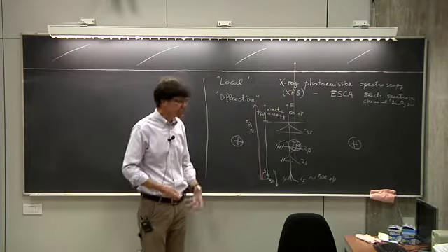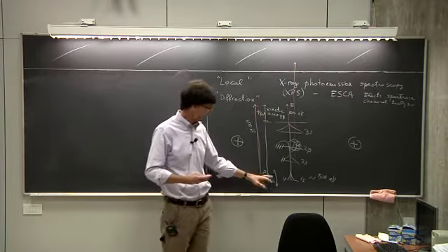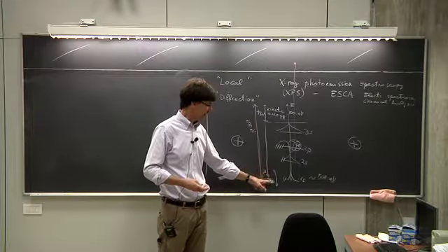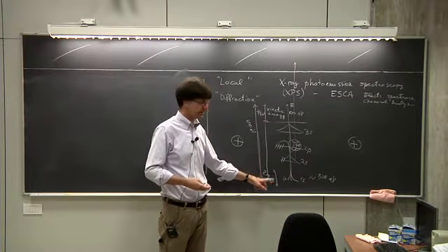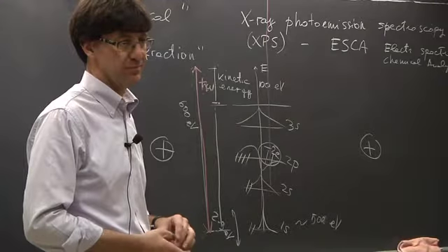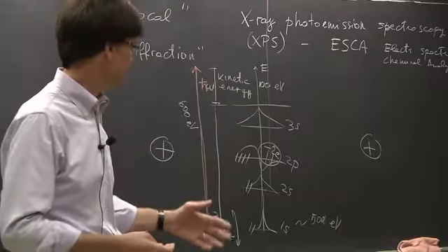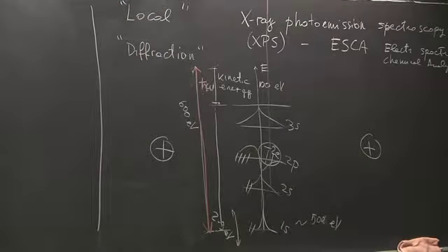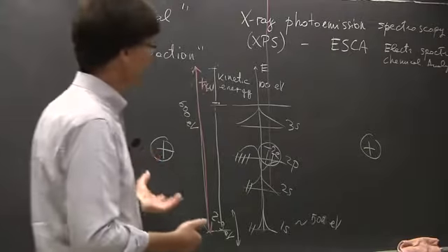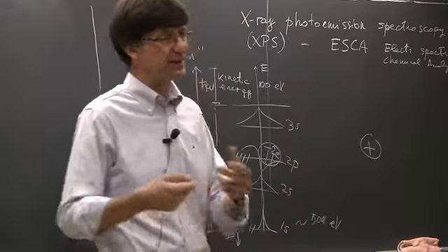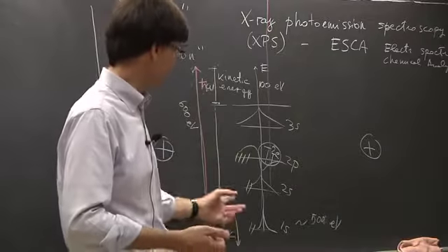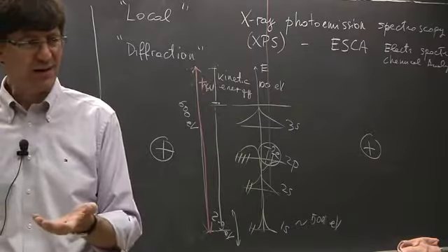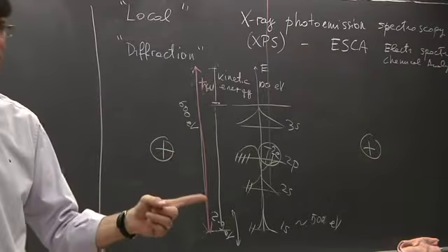Well, it's based on accumulated knowledge. You need to have information about how much the position of this binding energy changes due to the presence of nearest neighbors. It's not something that you can easily predict, but if you find a given change in a material that you know has 4 nearest neighbors, and you take another material with 6 nearest neighbors, and you find that the binding energy is different, then next time you do an experiment, you measure the binding energy, you compare whether it's closer to the 4 one or to the 6 one.